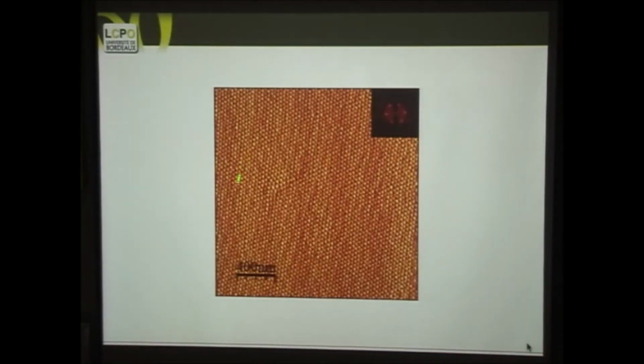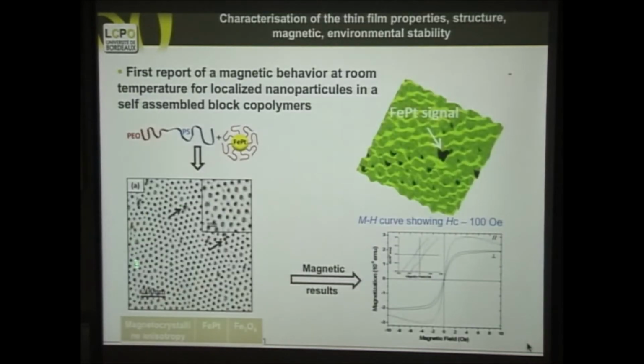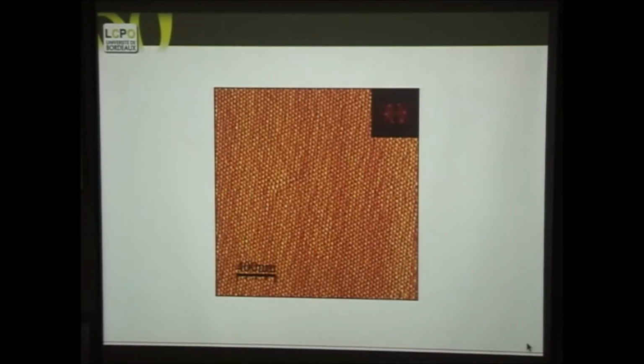And further, there is some new technology that unfortunately I cannot talk much about today, as it is under protection. We have developed a very simple technology where we can put this solution of the block copolymer with the magnetic particles and spin it over a surface, and you see them, they are organized perfectly over a very large surface. And actually tomorrow maybe the disk will be made this way, with this formulation of block copolymer with the magnetic particles. We will have this new technology of structuring the surface, put the film on it, and it structures itself immediately. So that will avoid a lot of processing steps.